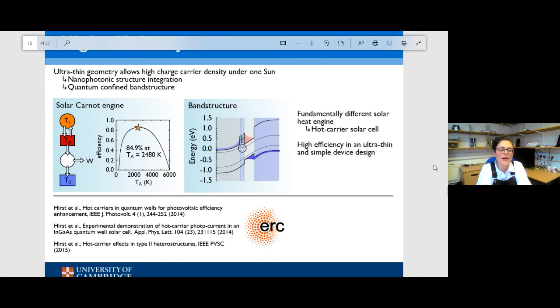But in fact, you can go a little further and things can start to get really quite exciting. So when you get to a much higher regime of charge carrier density, the materials start to behave differently, and you can actually drive these materials. We've seen it for III-V materials already. You can drive these materials into a regime where they are highly non-equilibrium, right? So you start to saturate out the lower lying states in the band structure. You can saturate out cooling pathways, so restricting your interaction with electrons and phonons to maintain a hot carrier population. You can also park charge carriers in satellite valleys within the band structure. So you can do all sorts of interesting things in these high carrier density regimes.